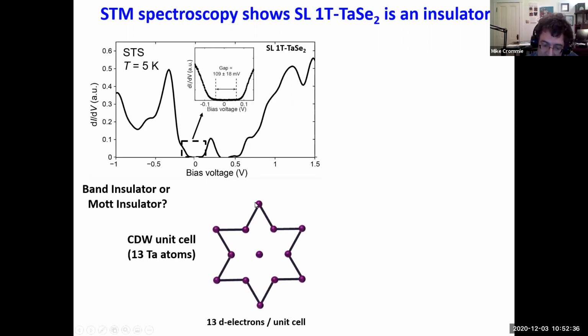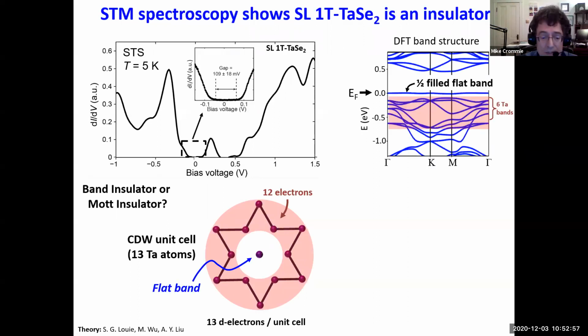Let's consider, for example, the unit cell of this material. The unit cell is the CDW unit cell, and there are 13 tantalum atoms. Each of them has 1 d electron. So we have an odd number of d electrons. So you might think, well, it should be a metal, by normal solid state physics reasoning. And in fact, if you do a density functional theory calculation on this material, which our theoretical colleagues did, then they indeed do see a metal when you do DFT.